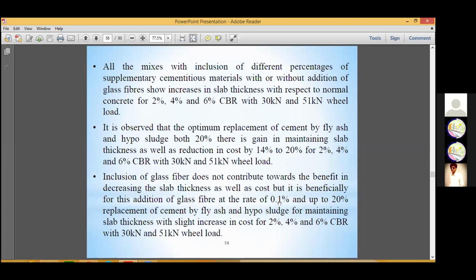And 0.1% glass fiber added, with up to 20% replacement of cement by fly ash and hypo sludge, for maintaining slab thickness with a slight increase in cost, for 2%, 4%, 6% CBR with the 30 kilonewton and 51 kilonewton wheel load.